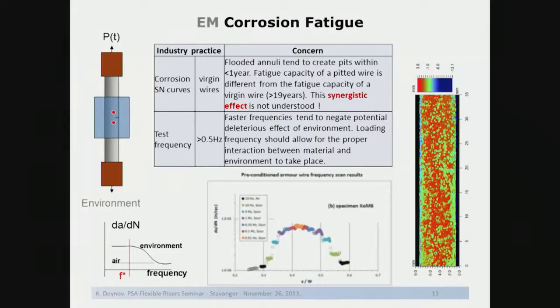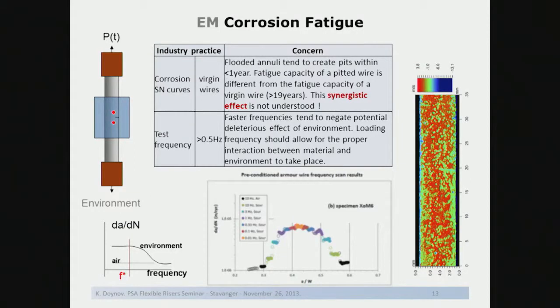So that is the methodology by which you are determining the maximum testing frequency for the given environment that catches all the corrosion chemistry properly. On this figure, what you see is really low test data following this approach. On the vertical axis, we have the crack growth rate. On the horizontal axis, we have the crack size, which is normalized by the width of the wire.